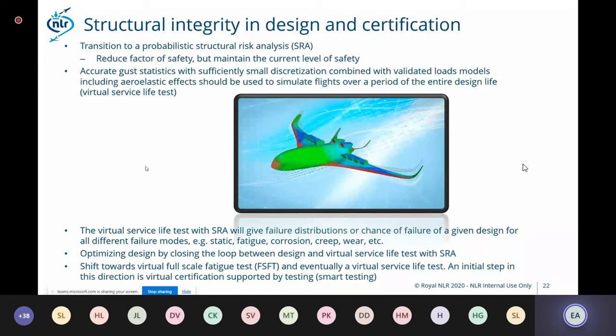So basically, if you then combine the virtual service life test with your structural risk analysis, you will get a failure distribution or chance of failure for all your failure modes. That's both static and fatigue, and you can incorporate creep and corrosion as well.